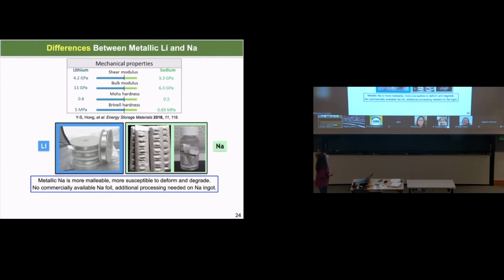If we look at the commercially available lithium or sodium we can purchase from Sigma Aldrich, you can actually buy very well-shaped lithium foil. However, for sodium, you will not get any well-shaped sodium. What you mainly get is something like this. We call it sodium cubes immersed in mineral oil. Of course, the surface is slightly oxidized, but the internal part of the sodium metal is still pretty shiny.